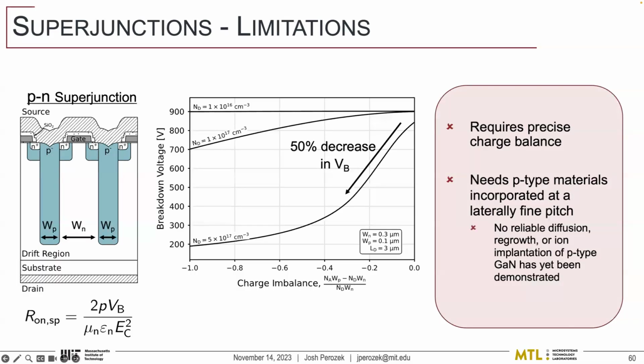They've been able to solve that in silicon, but the problem for gallium nitride is there's just really no way to dope these. Silicon can use ion implantation or fancy regrowth techniques. For GaN, that doesn't exist. There's no reliable diffusion, no regrowth, no ion implant that lets you change the carrier types within any of these regions. So that immediately rules out PN superjunctions as a problem that I can tackle without growth experience.